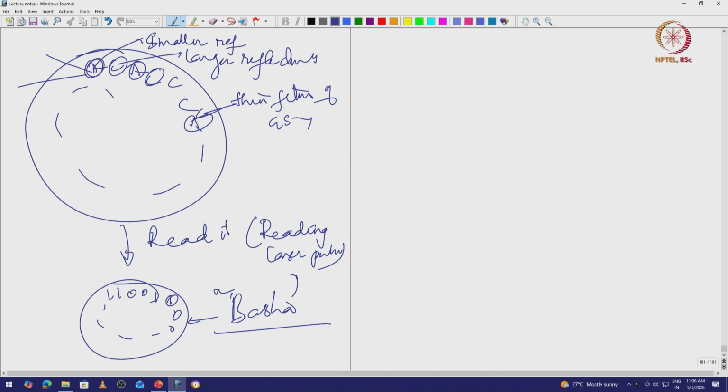Okay. So, this is how I used to watch movies using DVDs. The technology is simple. Now, the idea is when I have written the bit in an amorphous phase at room temperature, it is stable, for all practical purposes. It stays as an amorphous phase because there is no kinetics to form the crystalline phase. It is not that metastable phases cannot exist, they cannot exist infinitely.